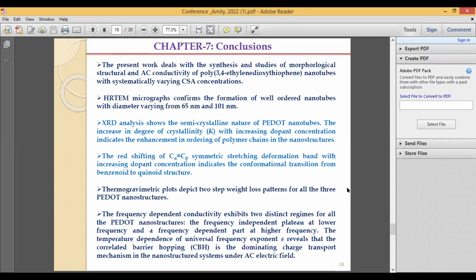In the Raman spectra, we have also seen that there is a conformational transition from benzenoid to quinoid structure. The thermogravimetric plot also shows the enhancement of thermal stability with increasing dopant concentration, which can be correlated with the XRD results. And finally, with the help of AC conductivity analysis, we can say that the transport mechanism in our system is controlled by the correlated hopping model. So thank you.